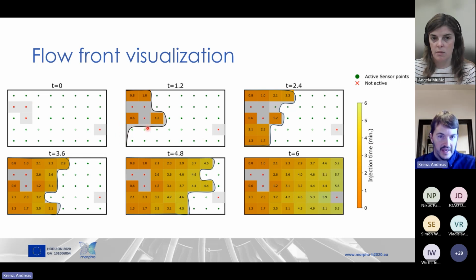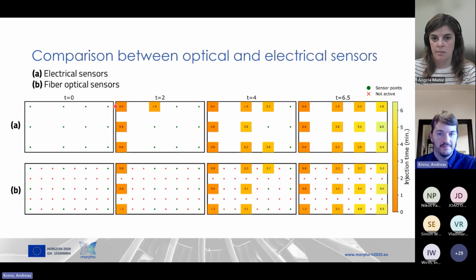And using this color-coded heat map, it's possible to have an idea about the shape of the resin flow through the whole FOD panel. And on the next slide, we used validation of the FBG data. So we used the comparison between the optical FBG and the electrical sensor data, which are from the same process. And as you correlate the data in detail, you see a good correlation of the flow pattern and also the arrival times. But there's an offset of this arrival time between the sensor techniques.